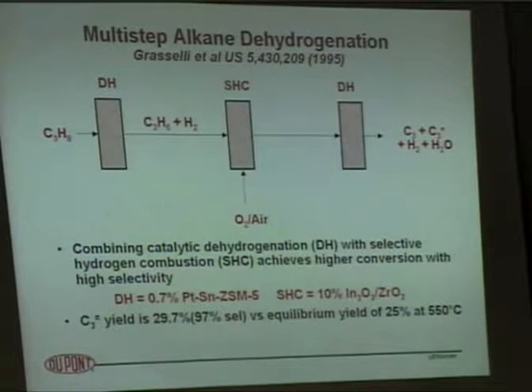That then allows you to shift the equilibrium again because the hydrogen has gone now to make water, and in a second dehydrogenation reaction the higher conversion will take place to give you propane, propylene, and hydrogen. In this oxidation reaction here, he was using an indium catalyst supported on zirconia. The net effect was an increase from 25 to 30% in the conversion. So, you know, it's a small but a significant step forward.